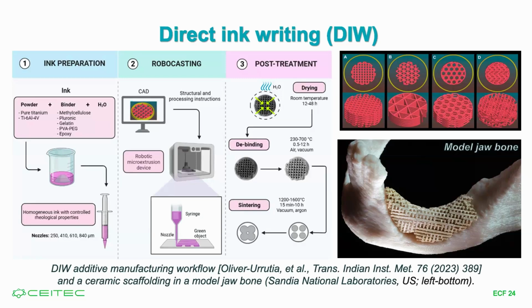But actually, this is one of the additive manufacturing methods where you can talk about printing, because this one has something called ink. It is prepared by mixing powder, which can be the same as for SLM or other methods, or you can also use some irregular shape powder here. You mix it with polymeric binder and water to achieve very specific rheological properties, which then allow you to use computer-aided design to print the object you want. And the final step is to dry out the water, burn out the binder, and at the last step, you do sintering for consolidation. And as with other additive manufacturing methods which use sintering, this allows you to control the internal microporosity of the material.